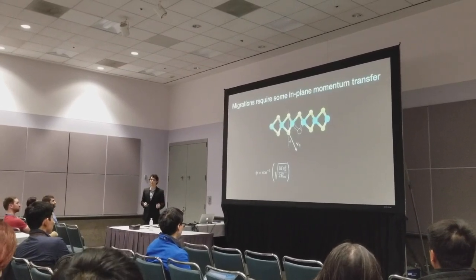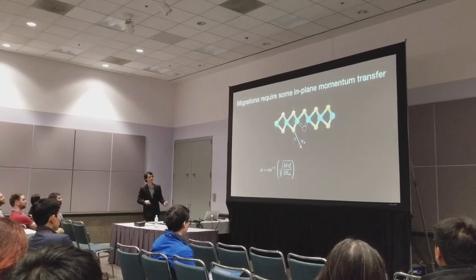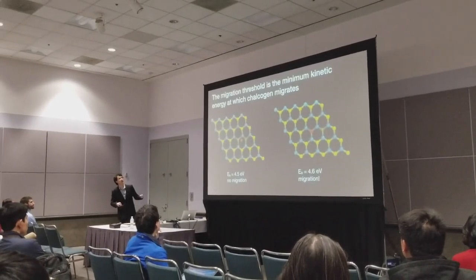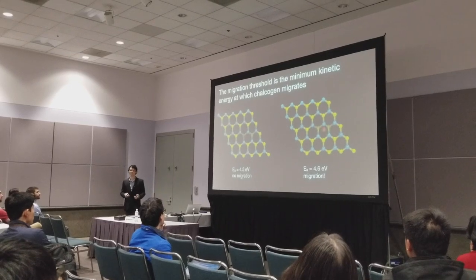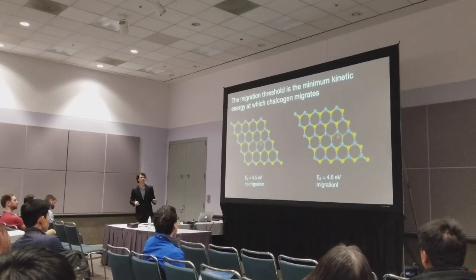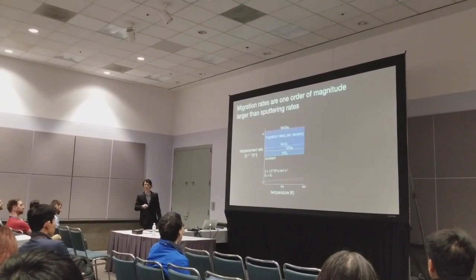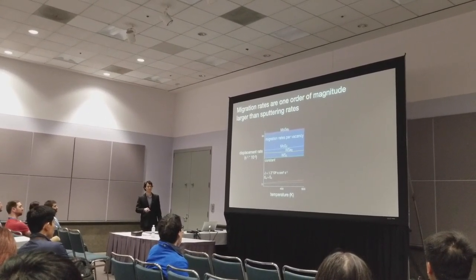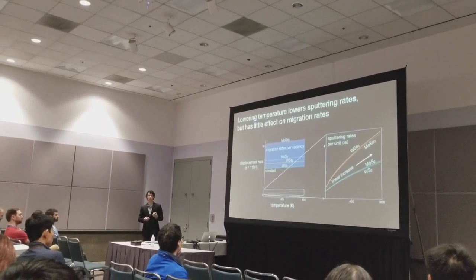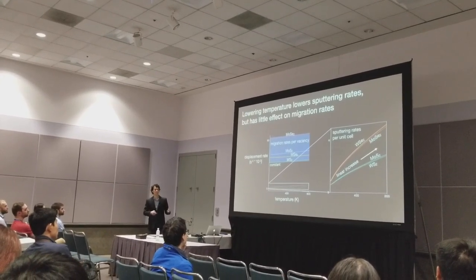With that in mind, we run molecular dynamics simulations for migration. We have an extra degree of freedom here — the recoil angle — since migration requires some in-plane momentum transfer. E_max in the denominator corresponds to the critical energy. The migration threshold is the minimum kinetic energy for which migration occurs, and we see that for WS2 and all the TMDs we consider, migration thresholds are much smaller than sputtering thresholds. Plotting all displacement rates as a function of temperature, migration rates are about an order of magnitude higher than sputtering rates and show almost no temperature dependence, while sputtering rates increase roughly linearly with temperature. By lowering temperature, we can limit sputtering rates without affecting migration rates, implying we can manipulate our material through migrations without significant damage from sputtering.